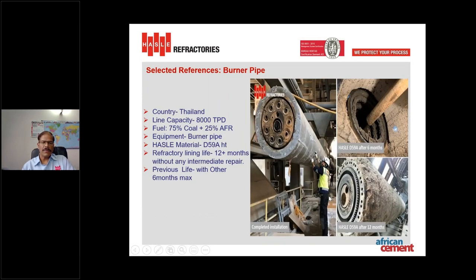This case is from one of the plants in Thailand, which has a line capacity of 8000 TPD and runs on 25% alternative fuels. They were not able to achieve a life of more than 6 months, and we installed D59A ht castable and they were able to achieve 12 months of life. You can see the picture after 6 months and after 12 months.